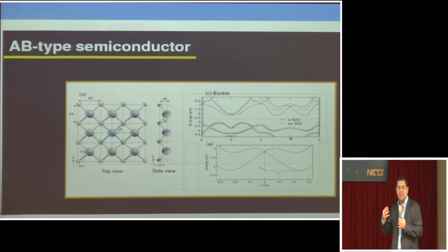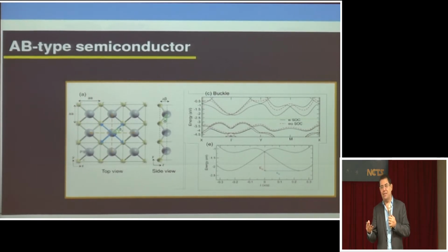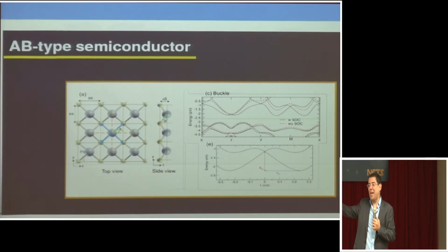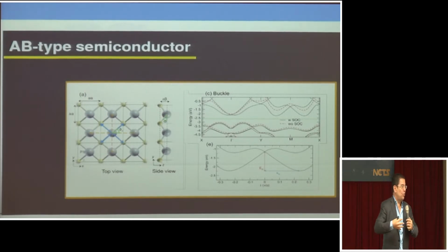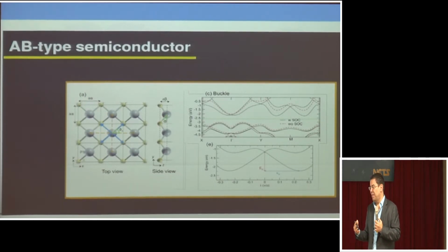So this is an example. We created numerically an artificial 2D lattice where you have one atom here, usually a heavy one. If you want very strong spin-orbit coupling, you choose a very heavy atom, because remember, spin-orbit coupling grows with the fourth power of the atomic number. So basic atomic physics. If you take an atom like lead, which is heavy, or bismuth, which is heavy, then spin-orbit coupling becomes very large, so you can explore this physics in a bigger way. But essentially it's like this.